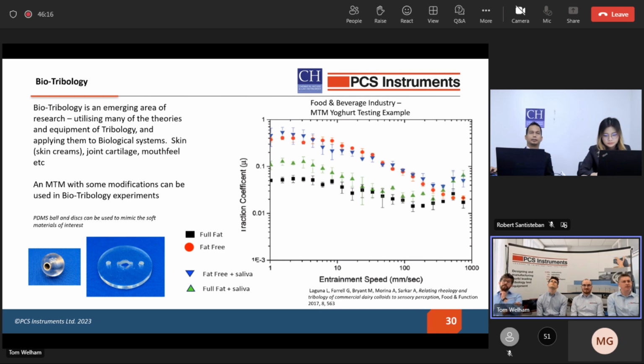We can use a variety of materials for looking at biotribological studies, but the use of PDMS for either one or both of the surfaces is very common in the literature. So we can adapt the MTM, as I mentioned, using the low load beam, which brings us to a load range of 2 to 8 newtons. And we can use it to look at artificial joints, mouthfeel, cosmetics, amongst many others, pretty much any biological contact